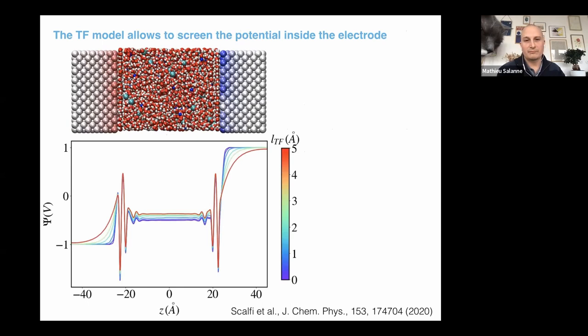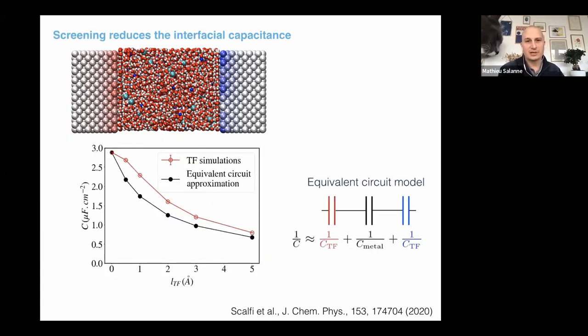So we first did simulations of a simple sodium chloride solution in contact with typical gold electrodes, and we changed the Thomas-Fermi length. And you can see that when you go from 0 to 5, you allow the charge to be more and more screened. And this impacts a lot the potential across the simulation cell. The liquid appears not to be much affected, because we always have the same oscillations inside the liquid part of the simulation cell. But on the metallic side, you see that there is more and more screening, and you recover the potential difference we apply, which is 2 volts, so we have -1 volt and 1 volt on the two electrodes, only after almost 10 layers, when the Thomas-Fermi length is quite large.